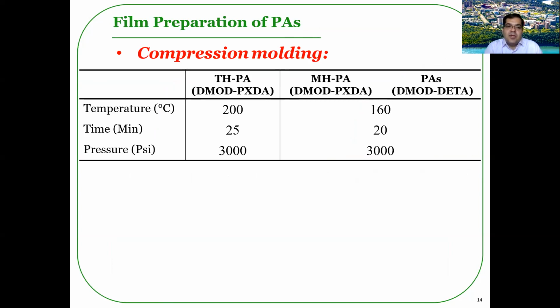The polyamide films were prepared using the compression molding method. The polyamides needed to be molded under about 3000 psi pressure. The required time and temperature for molding the polyamides was about 20 minutes at about 160 degrees centigrade, except the traditional polycondensed semi-aromatic polyamides DMOD-PXDA, which needed to be heated at 200 degrees centigrade for about 25 minutes.